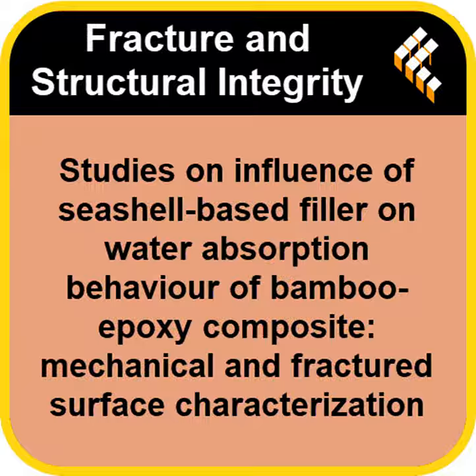Okay. And to double check, they weren't just grinding up random beach stuff. They did an elemental analysis, EDX. I confirmed calcium was the main element, about 50% by weight, which lines up perfectly with a high purity calcium carbonate composition. So they verified their waste stream was actually consistent and suitable. Good stuff. So consistent bamboo, consistent filler.